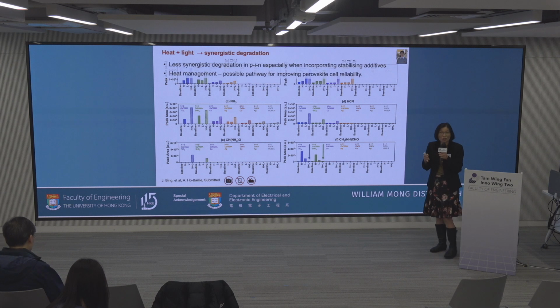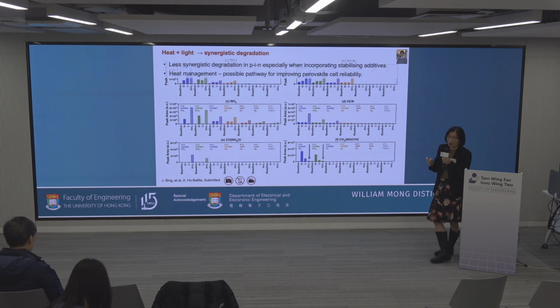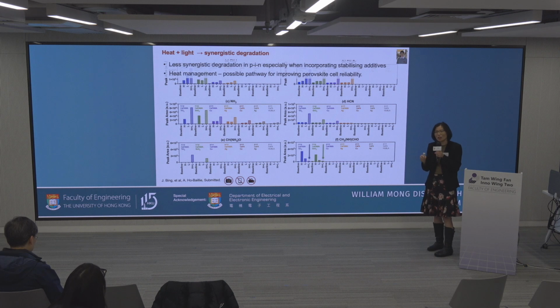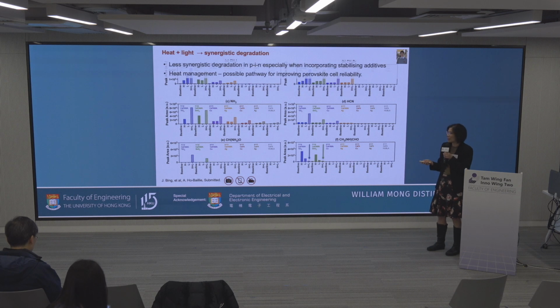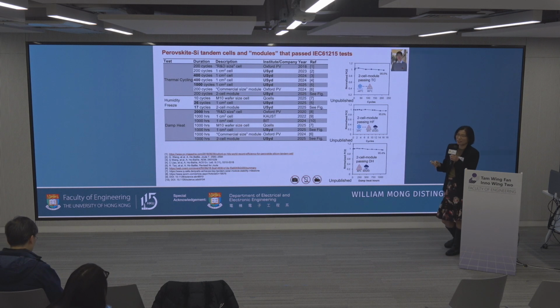So heat and light, when you combine them, yes, you get the synergistic degradation, but it's less so in PIN, especially if you're incorporating stabilizing active additives. So also, it is possible to make some perovskite cells more light stable. So what it means is, if you can manage the heat of the solar cell, if you can cool the solar cells down, and you can make the cell more light stable, it may be possible to improve the cell reliability, sort of to the extent of silicon.